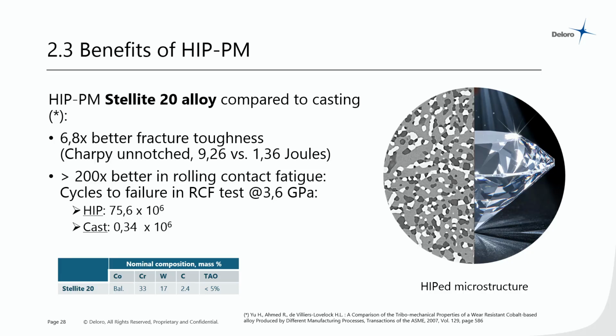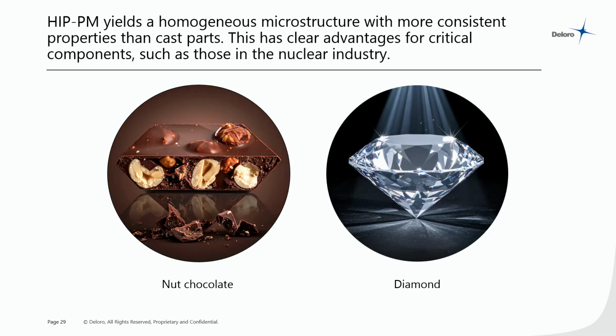And here's already a little clue as to our title page. You can see that we're comparing the HIP microstructure to a diamond because it has a homogeneous, consistent structure. Whereas, if you think about that cast microstructure that we just saw 2 slides ago with those big carbides, that is a little bit more like the carbides being the nuts in the softer chocolate cobalt chrome alloy matrix. So now you also know that we're halfway through this presentation, slightly over halfway.